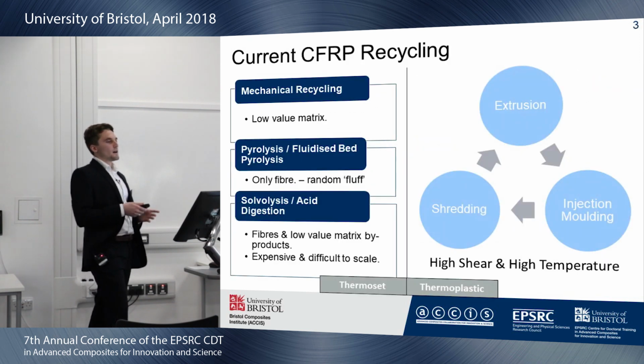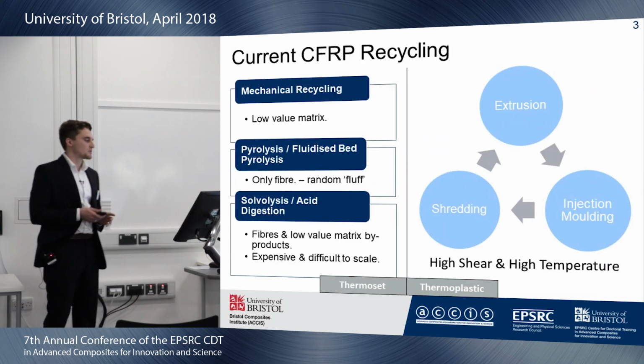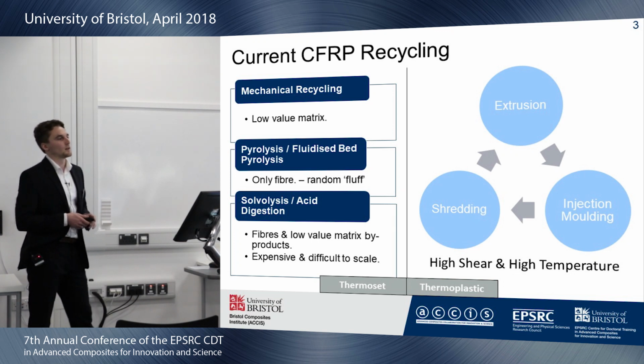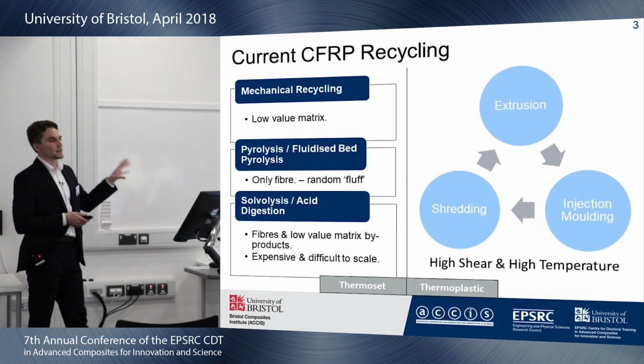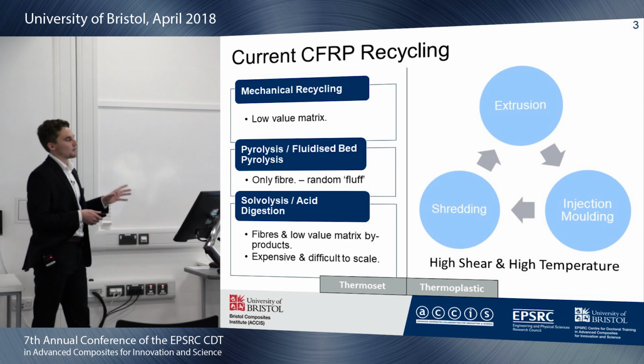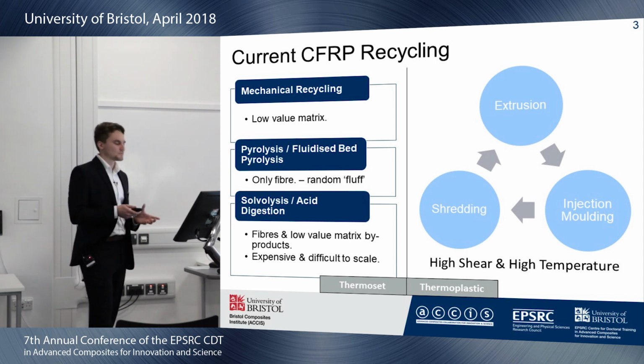So currently, carbon fibre reinforced polymers are principally landfilled. Second to that, thermosets are mechanically recycled. From this you get a low value recyclate powder, which is a really low quality. If you want to reclaim your fibres, you can use pyrolysis or solvolysis, and you can get some good properties from your fibres close to virgin. You don't really get any properties back from your matrix that's lost.